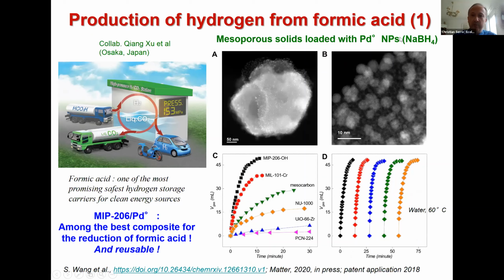The palladium nanoparticles are usually formed by using sodium borohydride. So they tested immobilization of the same amount of palladium nanoparticles in our MOF and compared that with benchmark MOFs like MIL-101 or NU-1000 and a mesoporous carbon. And our material behaved the best, with the highest activity. And then it was fully cyclable for 5 cycles at least, while in some cases like NU-1000 and so on, they have seen some degradation of the MOF.